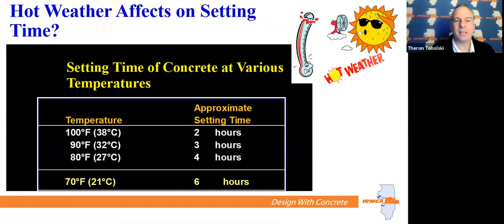How does hot weather affect set times? We talked about cold weather. Let's look at hot weather. If we had our typical 70-degree concrete, that concrete mix would set in 6 hours. But when we get to 80 degrees, we go to 4 hours, 90 is 3, and 100 degrees is 2.